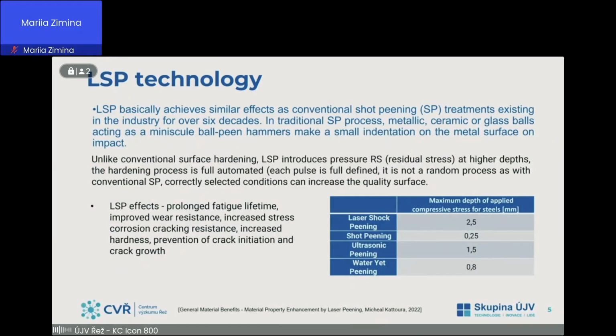And I would like to say a few words about LSP technology. LSP, laser shock peening technology, or laser peening, it's very similar. LSP basically achieves similar effects as conventional shot peening treatments existing in the industry for over 6 decades. In the traditional shot peening process, metallic, ceramic, and glass balls, acting as minuscule ball peen hammers, make a small indentation on the metal surface on impact. Unlike conventional surface hardening, LSP introduces compressive residual stress at greater depths. It's very important. And the hardening process is fully automated. Each pulse is fully defined. It's not a random process. We can simulate the process very well and better set up the process for the hardening.